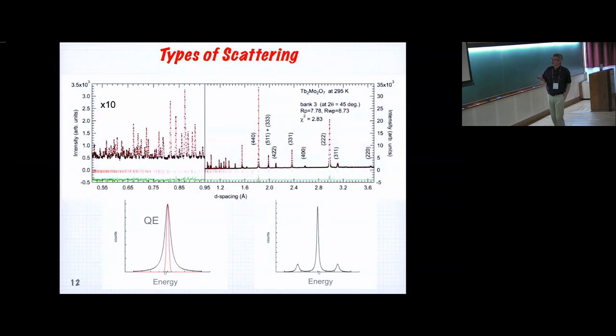Inelastic neutron scattering, where you have your elastic line, which comes from these peaks, or even here, they'll be very intense. The inelastic features, the spin waves, the magnons, the spinons, are at least a factor of 10 down in intensity on every material, rule of thumb. So you're looking at the background position, and then you want to do the inelastic, you drop down a factor of 10. If you sit on top of the Bragg peak and you look at the inelastic, you have to go out quite far out in energy before you are invisible to that Bragg peak. And so there's a tradeoff at how close to these Bragg peaks you look. And then to get the full dispersion curve, of course, you want to move between Bragg peaks.